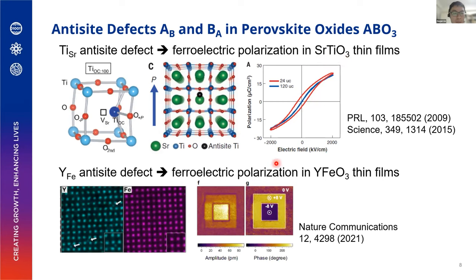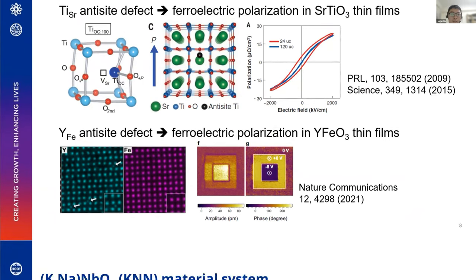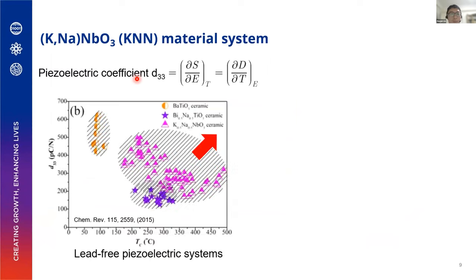Similar phenomena have been found in other material systems such as yttrium ferrite, where yttrium occupying the iron position also can give rise to some ferroelectric behavior. So our idea is to use these anti-site defects to introduce higher piezoelectric and ferroelectric behavior in a sodium niobate-based system. This is a well-known system among the so-called lead-free piezoelectric materials.